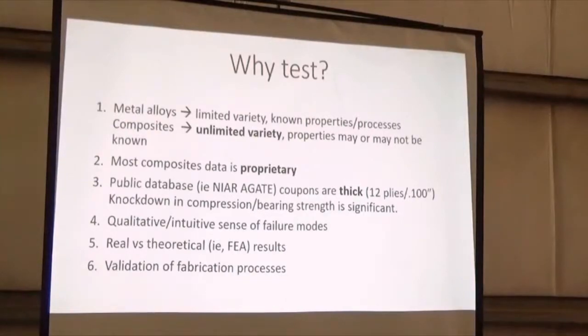But a lot of those test coupons are relatively thick. They typically do 12 plies. It's about 1/10 of an inch thick. There's reasons for doing that because it makes it easier to do your tests, but we rarely use that many layers in a small GA airplane or a drone or whatever. I mean, typically we use 2 or 3 layers, and sometimes you could get away with 1 layer if it wasn't for gauge thickness factors, i.e., you want to be able to not have somebody put their finger through something, and if you only have a single layer, it might be strong enough from a structural point of view, but you're going to have really bad hangar rash issues.